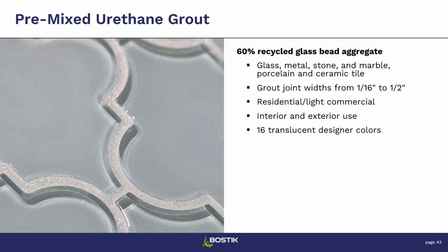With recycled glass beads, it's about 60% recycled glass. It can be used on glass, metal, stone, marble, porcelain, and ceramic tile. These are good for grout joints that are 1/16 to 1/2 of an inch. And again, very similar to the sanded one. It's used for residential and light commercial application, as well as interior and exterior use. Usually there is a range of colors. It's not as big as it is with a traditional quartz grout that's in the pre-mixed urethane. So there are 16 translucent designer colors that can be used with this.